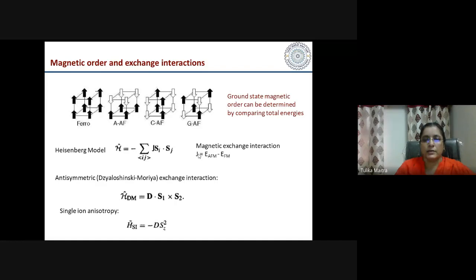This J, which is given by the difference between the antiferromagnetic state and the ferromagnetic state, can be calculated by mapping the total energy difference to this kind of Heisenberg model. One can calculate this magnetic exchange interaction. Similarly, the Dzyaloshinskii-Moriya exchange interaction also can be calculated. The value of this D can be calculated, or the single ion anisotropy energy also can be calculated.